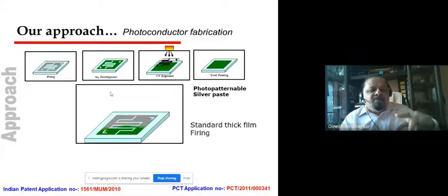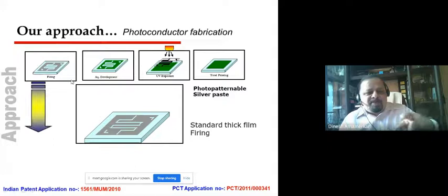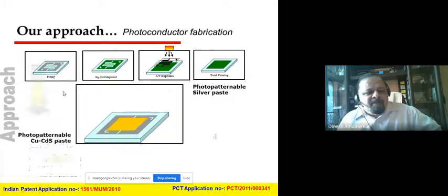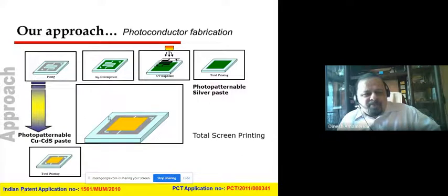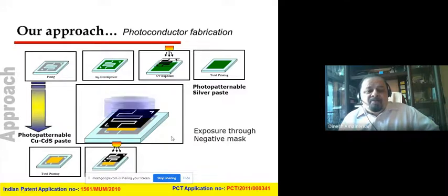How? Let us see. After the aqueous development, we subject this pattern to typical thick film firing at 800 degrees centigrade for a 1 hour firing cycle with peak firing of 10 minutes. And when the thick film gets matured, the electrode gets matured like this, we deposit photopatternable copper-doped cadmium sulfide paste, which has been formulated in our own laboratory. Here, we do the same steps. Here we screen print on the previously printed silver electrode pattern.